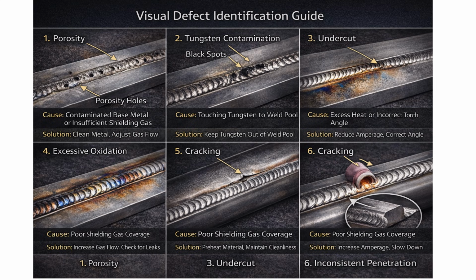Undercut, that groove along the weld edge, means you're moving too fast or your amperage is too high. Slow down and reduce heat. If you see excessive oxidation or discoloration, your gas coverage is insufficient. Increase flow rate, check for leaks, or add trailing shields for materials like stainless steel and titanium.